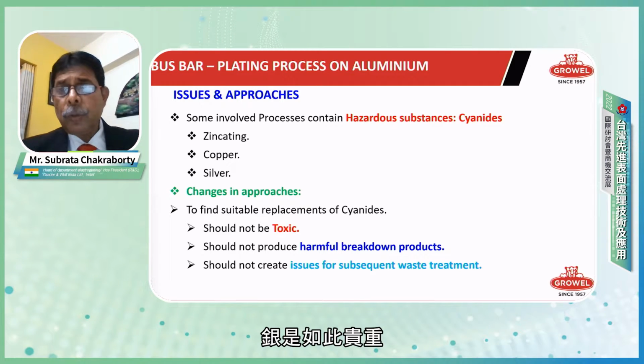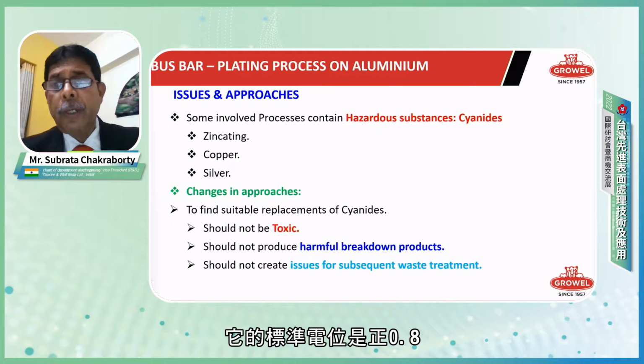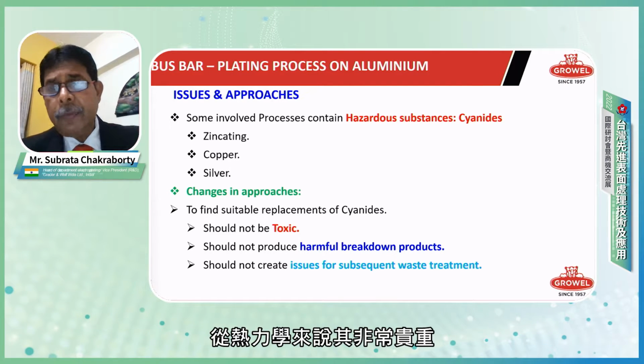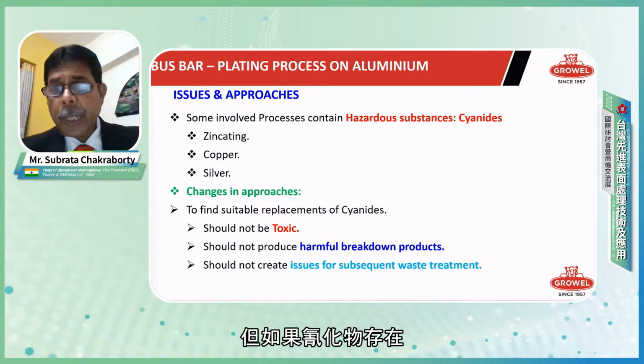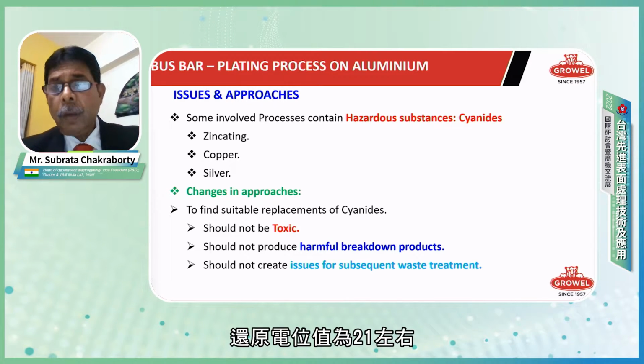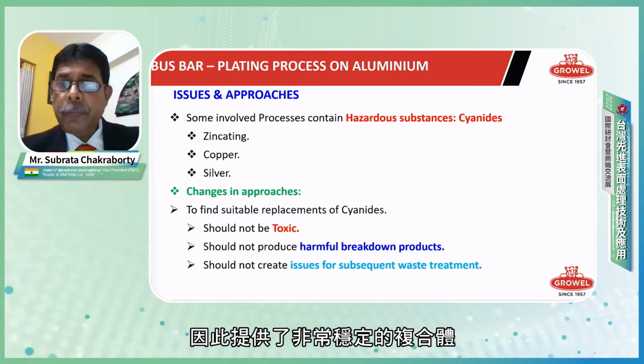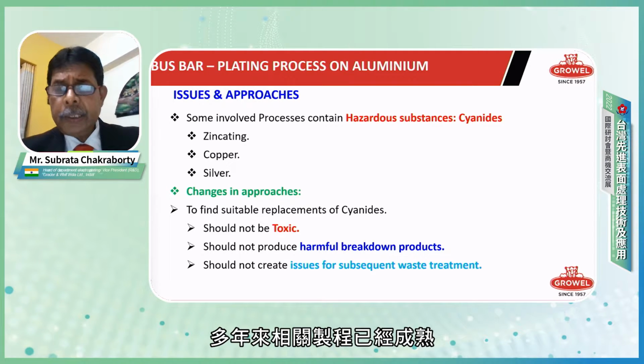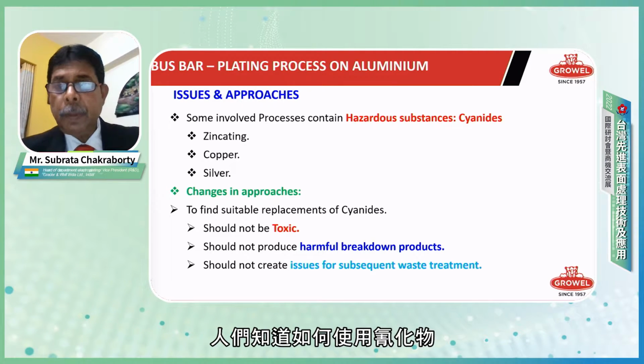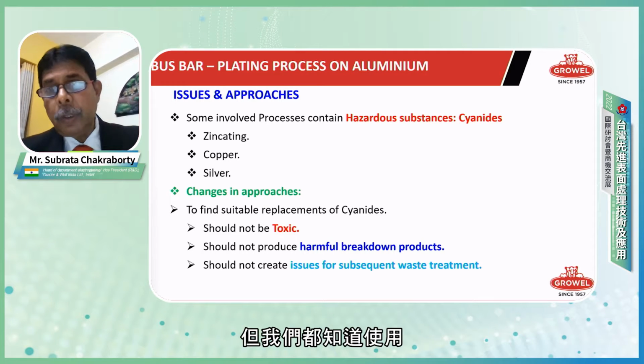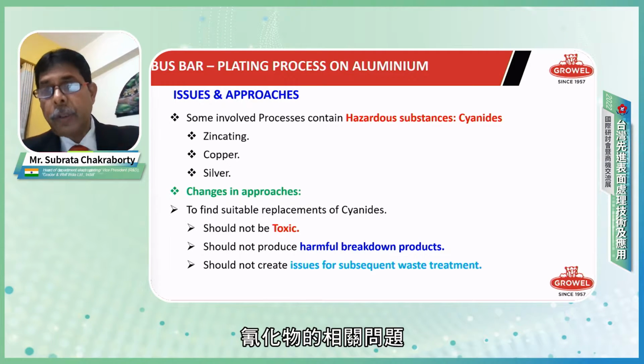Silver is so noble, with a standard electrode potential of positive 0.8, so thermodynamically it's very noble. But in presence of cyanide, it forms silver cyanide as a complex, with a log K value around 21. This provides a very stable complex, and over the years this is totally established and people know how to use cyanides, but we all know the issues associated with using cyanide.